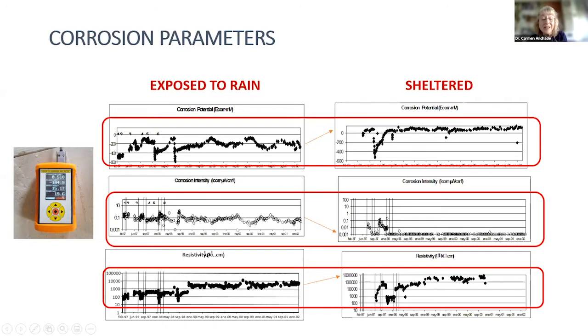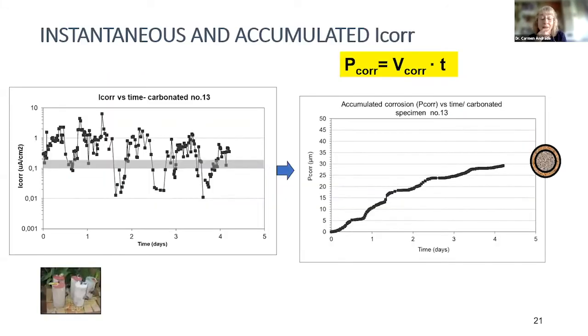About the corrosion rate, again, in the protected specimen there is no corrosion at all, the corrosion rate is very, very low, while in the case of exposed to rain, I think that this specimen is carbonated, we are above 0.1, that is the threshold that I was commenting on before. Sometimes that depends on the amount of water that is inside, and the resistivity is 1 order of magnitude higher if it is dry, of course, than when it is wet. In that case, the corrosion parameters follow the effect.